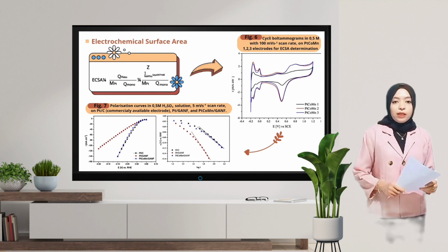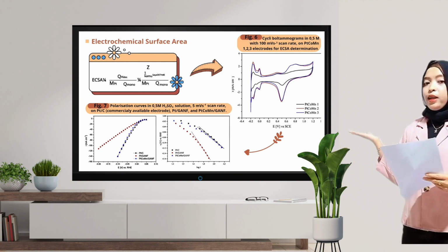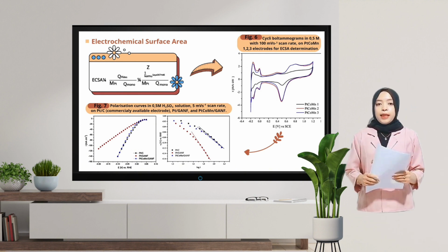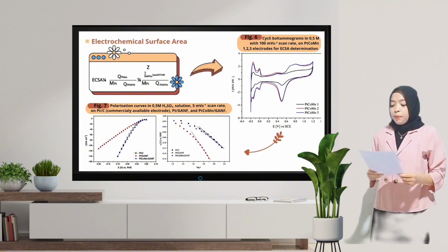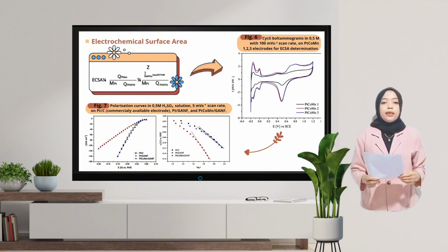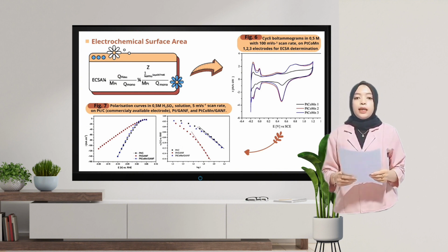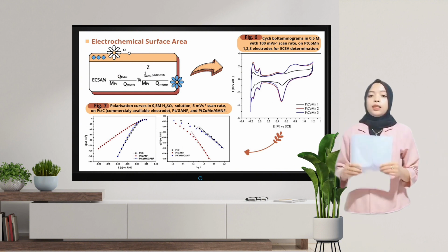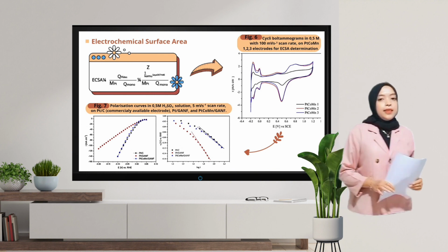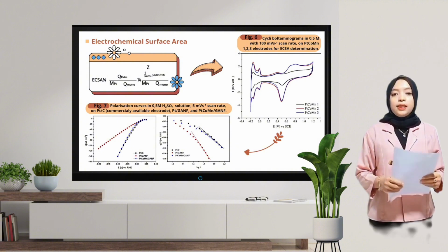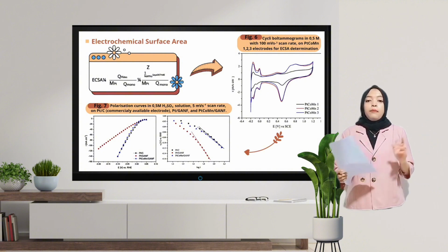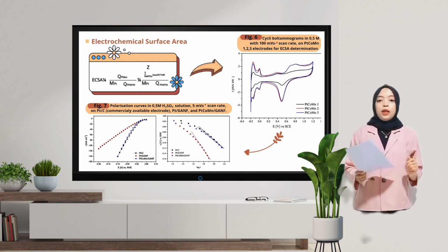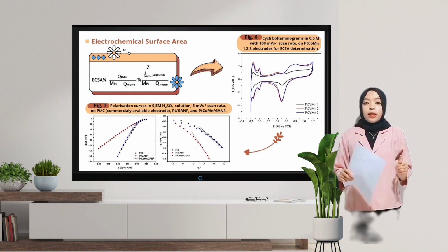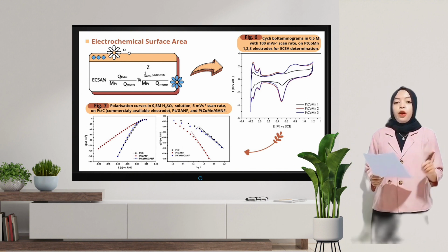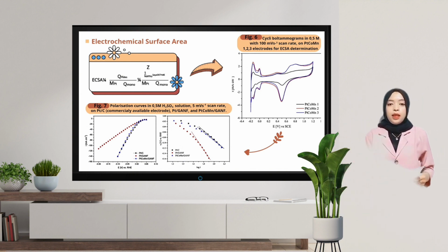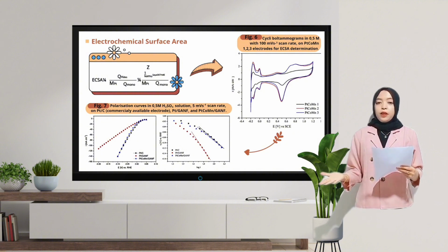The electrochemical surface area was determined via cyclic voltammetry in 0.5 molar sulfuric acid with a scan rate of 100 mV per second in the same cell configuration as for catalyst electrodeposition. The ECSA is calculated assuming that only Pt is electrocatalytically active, by integrating the area under the hydrogen desorption peaks between -0.2 versus SCE and 0.1 versus SCE, as illustrated in Figure 6 and Figure 7.